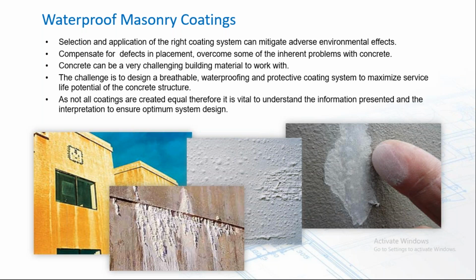You know, we're faced with laitance or dusting on a concrete surface due to perhaps overwatering of a concrete mix, and that creates a bond breaker right there, as you see on the right. The high moisture content in concrete, 5% and above typically, can create issues with vapor drive, and I'm sure most of us online here appreciate the blistering that might occur on a coating when concrete is moved into the sun or shortly after coating. And then the high pH of freshly poured concrete or stucco can damage poorly chosen coating systems with alkali burn or saponification, and that example there on the left. And then, of course, our old enemy of efflorescence occurring due to moisture within the structure, liberating these soluble salts to the surface.